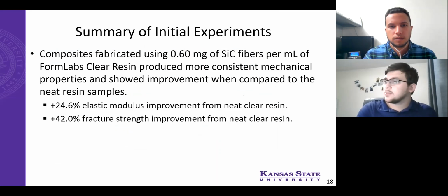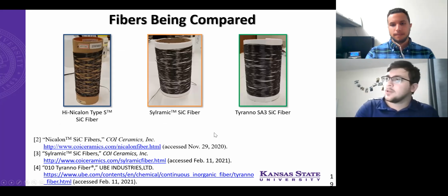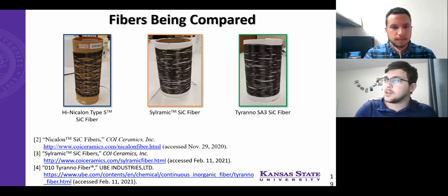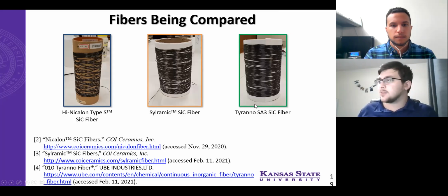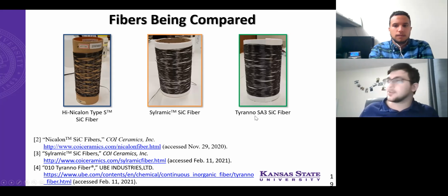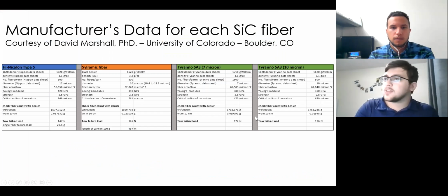I see. So in summary of the initial experiments, we decided to go forward with the 0.6 milligrams per milliliter. They showed an improvement of 24.6% for elastic modulus compared to the neat resin, and 42.0% when comparing fracture strength to that neat resin. So we can jump into the fiber comparisons now. Again, we tested the Hi-Nicalon Type S, the Sylramic, the Tyranno SA3. And there's that manufacturer's data again.